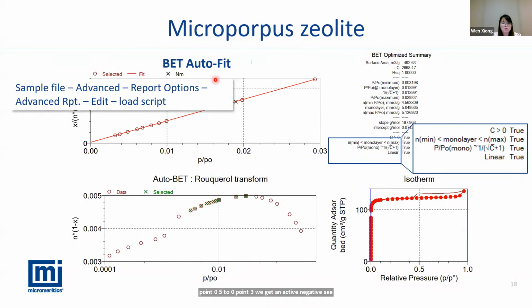Then we jump to using the BET auto-fitting script. This is the process of how to use the script to do the data reduction. And then we are able to see here, we get a C constant value which is larger than 0. That makes sense for us. And then the other 3 criteria of using the BET equation are also checked here. So that means using our BET auto-fitting script, we are able to apply the BET equation for the microporous materials. In this example, the zeolite materials, the data points used for the BET calculation were taken in a relative pressure range which is very different from the regular BET relative pressure.